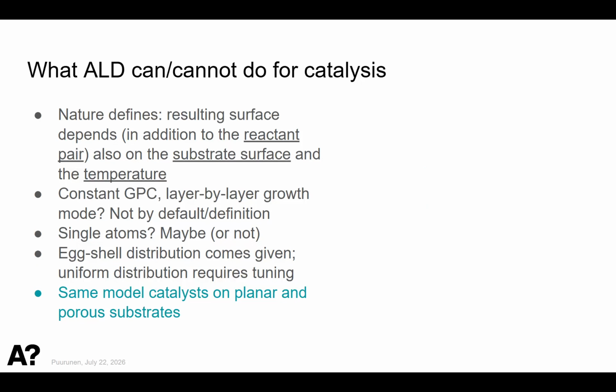And where I think ALD will be powerful for scientific research is where you want to have the same kind of surface on planar and porous substrates. So if, when you are making your porous material, you have pieces of silicon, for example, present in the same reactor at the same conditions, to my understanding, you should have the same coating in both cases. It does not work the other way around, that you would place your porous material next to an optimized thin film process, because there the exposures will very likely be too small for the porous material to get coated, but the other way around should work. If porous material gets a nice coating, then also the flat wafer will get it.